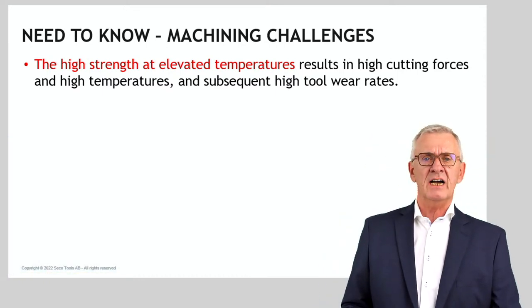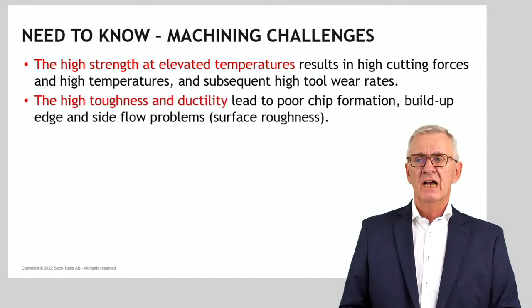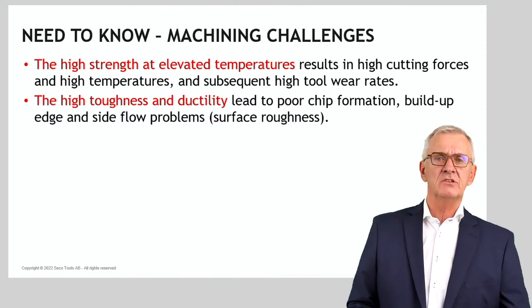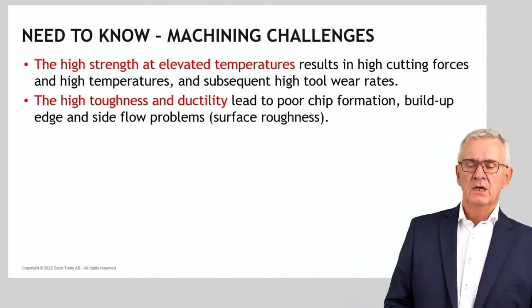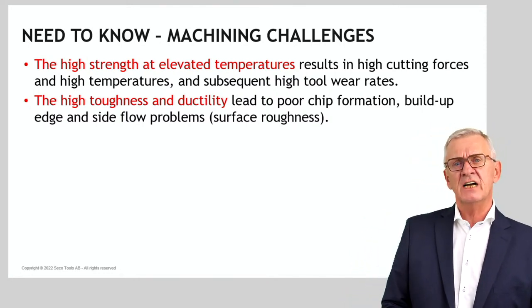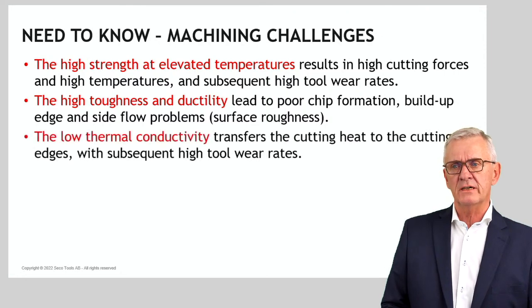High strength at elevated temperatures is typical for these materials. It gives us high cutting forces, higher than what we expect from the traditional hardness of the materials. High toughness and ductility gives us bad chip formation, built-up edge risk, side flow effects. We should be aware of that.